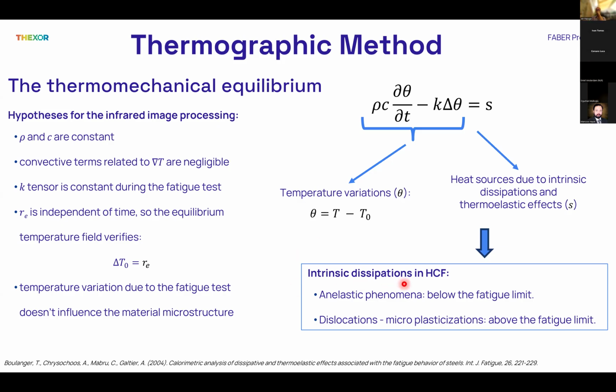Focusing on intrinsic dissipations, the factors involved during heat generation differ depending on the load. In case of low stress amplitude, below the fatigue limit, heat generation is mainly caused by anelastic phenomena. On the other hand, for high stress amplitude above the fatigue limit, heat generation is mainly caused by movements of dislocations or microplasticization effects.